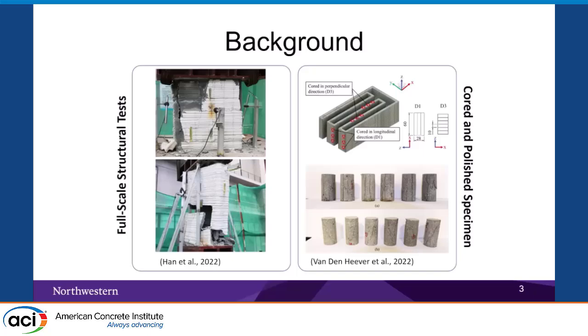For the first method, large-scale testing, all the reported work had a lot of variability in the results, because of different defects in the material related to surface defects, interlayer defects, or also the printing system. The second method, cutting or coring samples out of a 3D printed structure, eliminates the 3D printing features. So eventually we are converting the 3D printed element to kind of a cast element. That's why we wanted to go a step further in this matter.